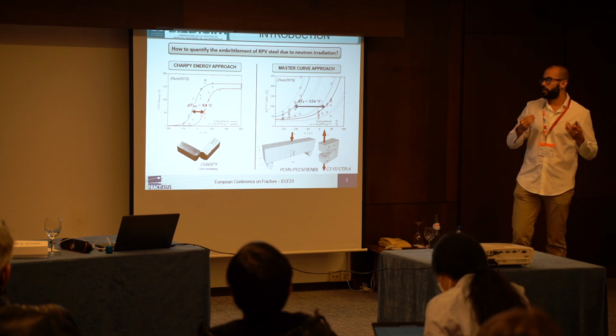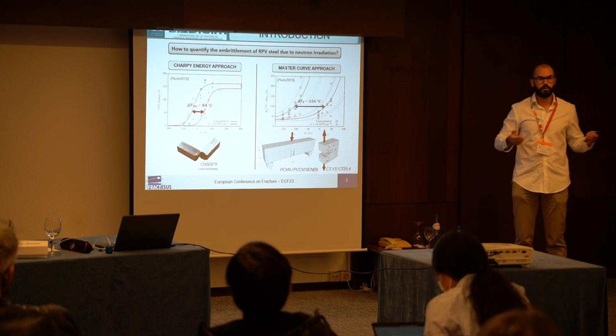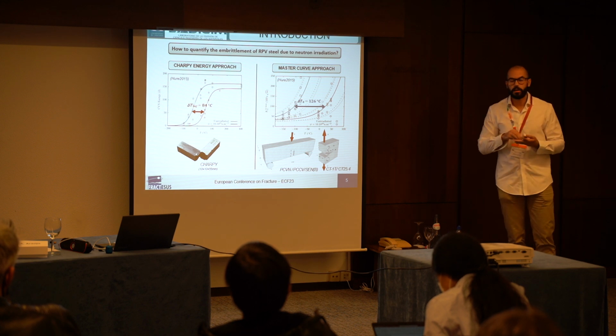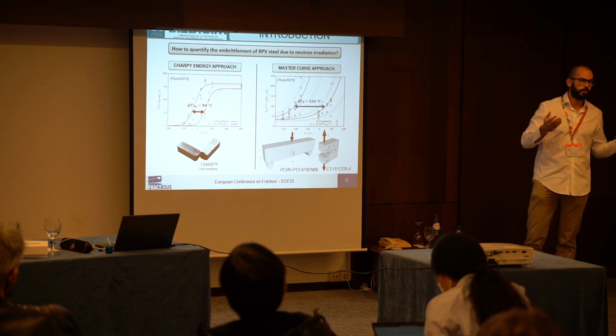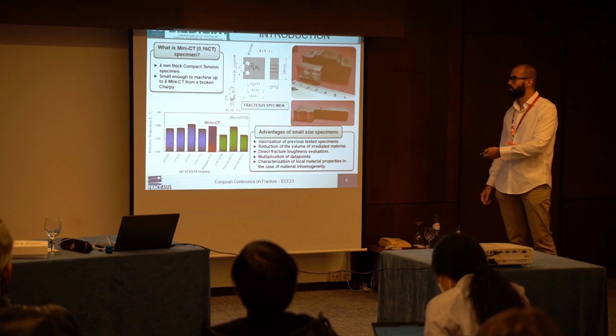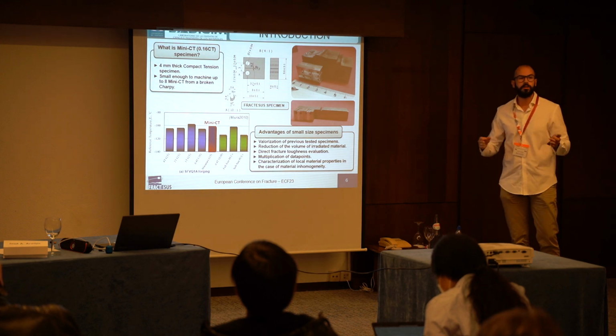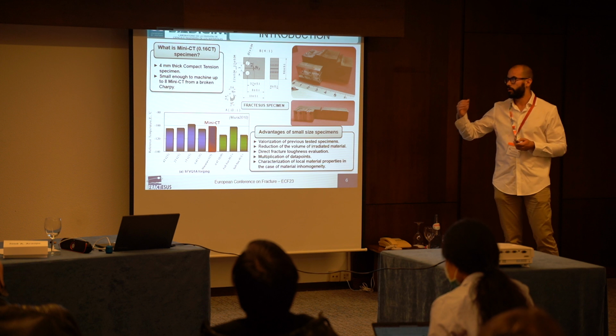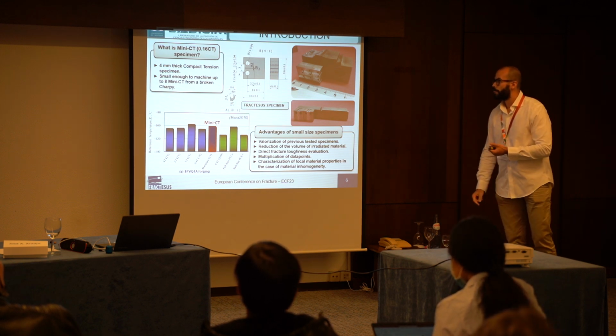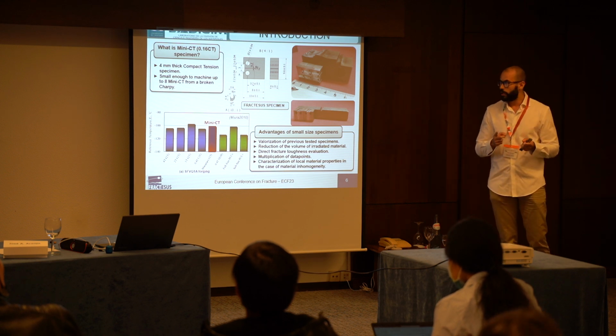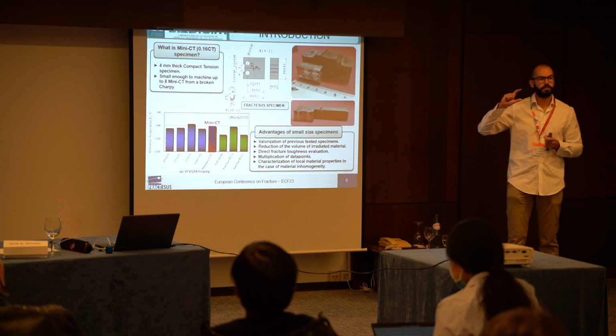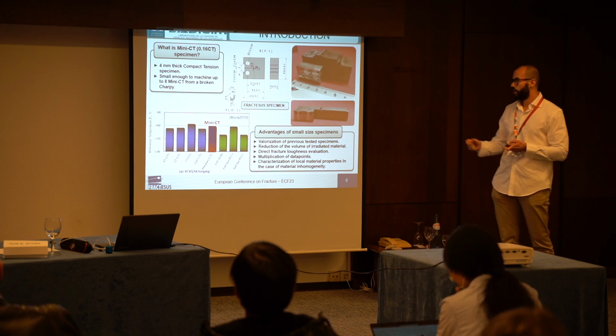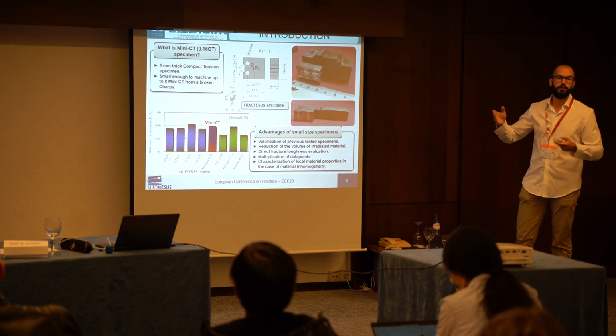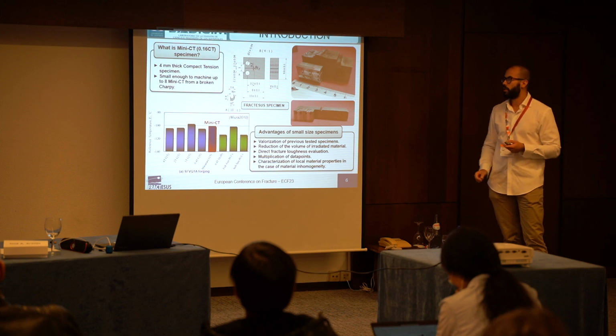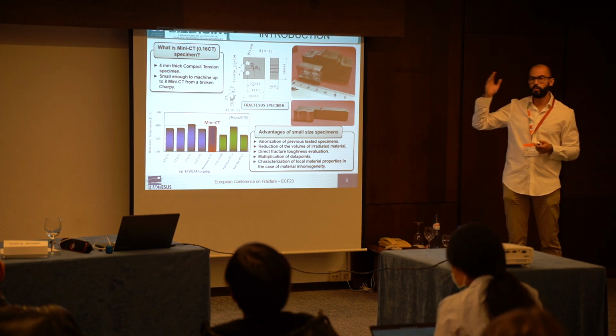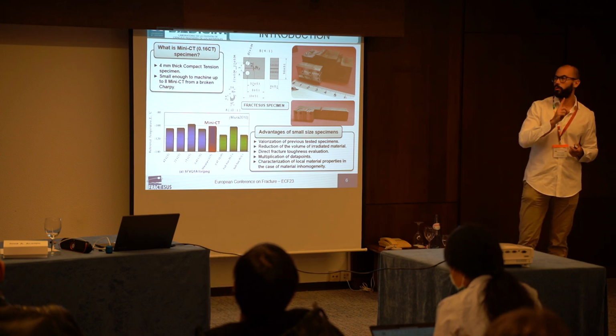The important thing here is that in order to perform this test, you need, of course, material, and the current nuclear power plants are running out of material. So, in this sense, a new proposal was introduced by using the miniature compact tension specimen with the master curve approach. This specimen that you can see in the figure has the dimensions of 10 millimeters by 9.6 millimeters by 4 millimeters of thickness. This is the standard specimen proposed by FRACTESUS, but of course some of the partners are using slightly different specimens.